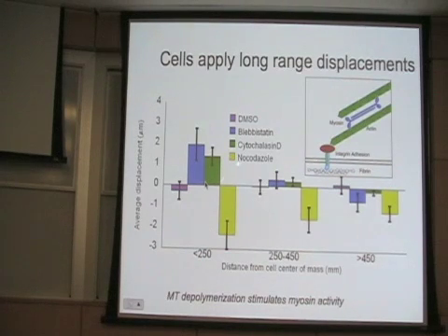And here's kind of an interesting thing. If you don't depolymerize the actin, but instead you depolymerize the microtubules with nocodazole, the cells pull harder. This is a well-known phenomenon that depolymerizing microtubules often releases small GTPases that will activate myosin even more. And by doing this, by putting in active contractions, now we can actually see statistically significant deformations half a millimeter away from the edge of the cell. So how is the cell able to do that?